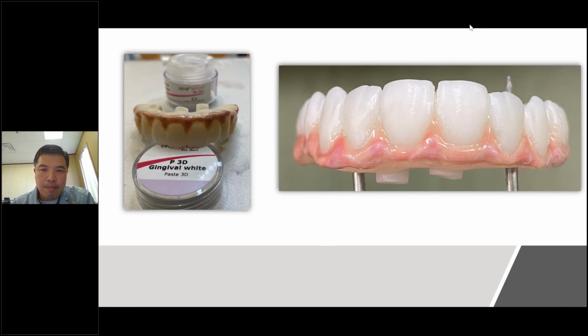Why is that considered important? It is because zirconia doesn't release heat correctly. Okay, it releases heat really slowly. So if we go through the same cycle as what the manufacturer recommends us to use, the zirconia will fracture on us. Doesn't matter if it's Zirlux or Ivoclar Prime or even Noritake hybrids, they all will fracture because the cooling takes forever.